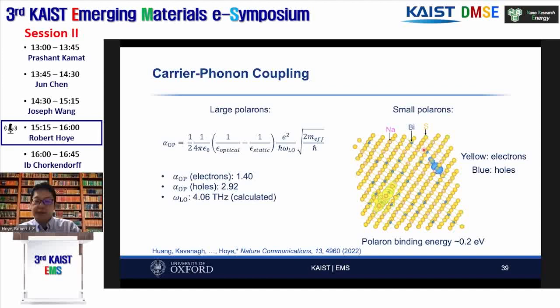And what we found here was that the holes all localized around the sulfurs with a high coordination of sodium. If you think back to what I said earlier, when there's high coordination of sodium, that means we have these states, sulfur p states, forming within the band gap close to the valence band. So probably what's happening is that those localized states are trapping the holes very soon after photo excitation. And then after trapping the holes, the lattice distorts around that to form a small polaron that's very hard to move between different states.